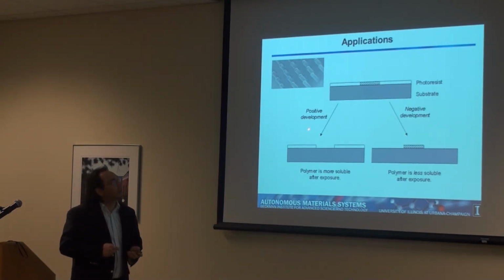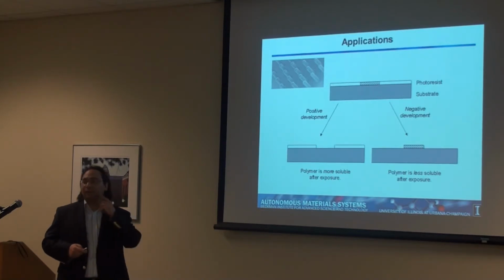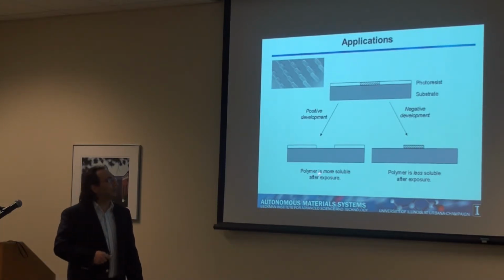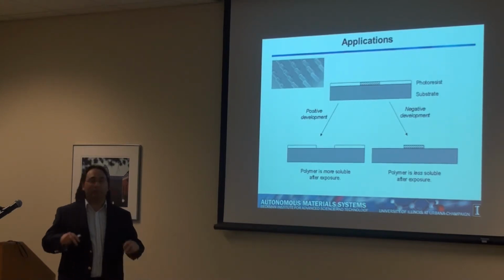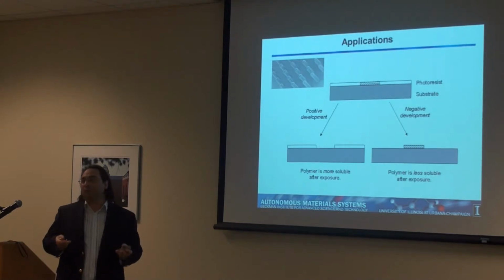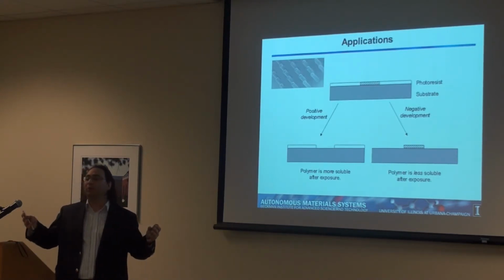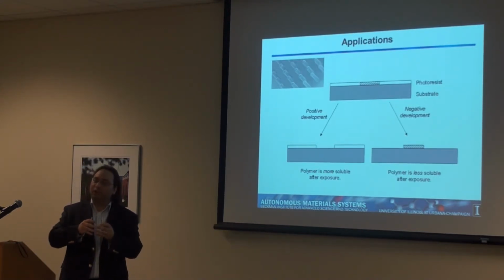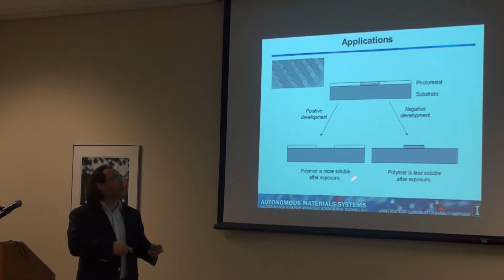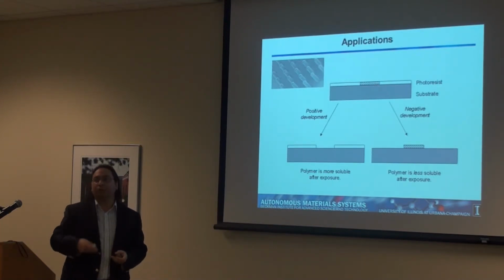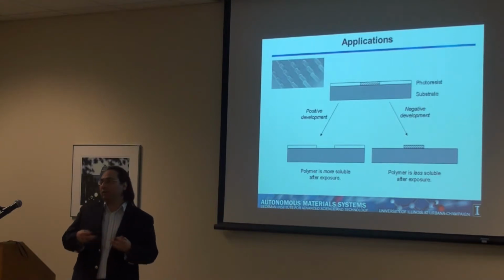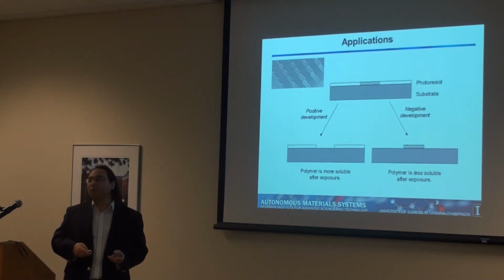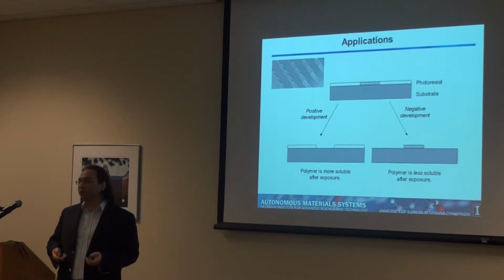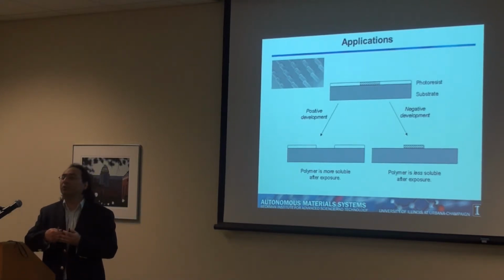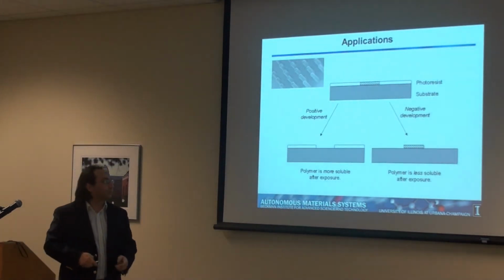So there are positive photoresists and negative photoresists. With positive photoresists, you have your polymer, and where you shine light, it becomes more soluble. For example, it depolymerizes. You have a polymer, you shine UV light, it becomes a monomer again, then it's soluble, and you can take it off. And the negative is the opposite. When you shine light, it becomes cross-linked and insoluble, and that's actually the chemistry that we want for self-healing systems, making new bonds inside your material.